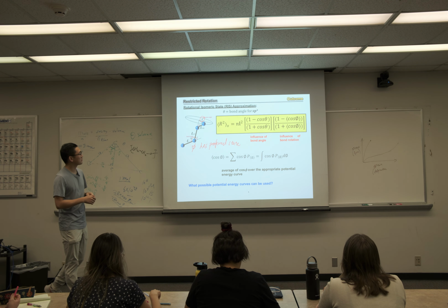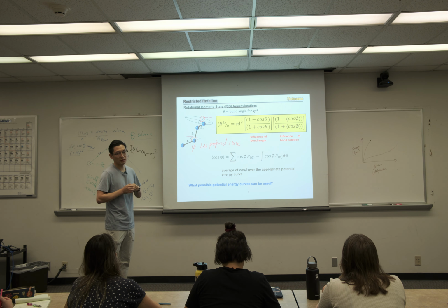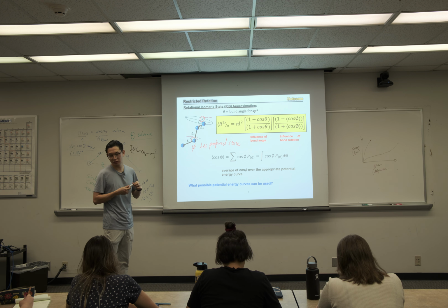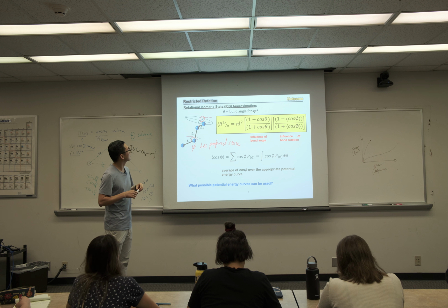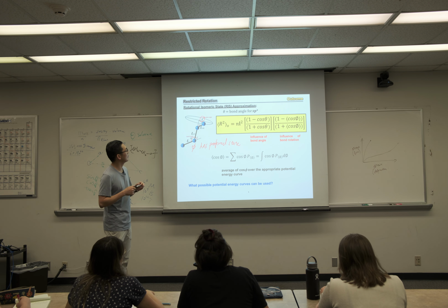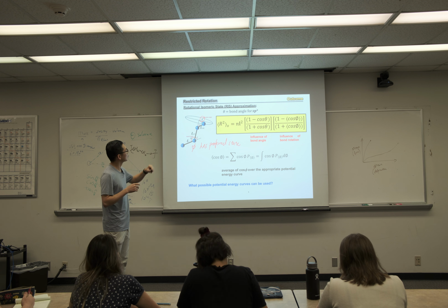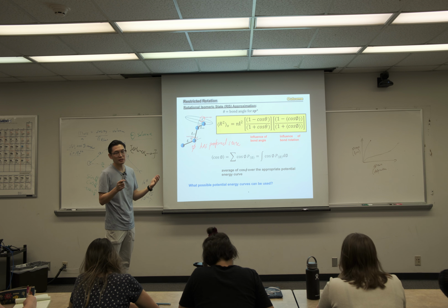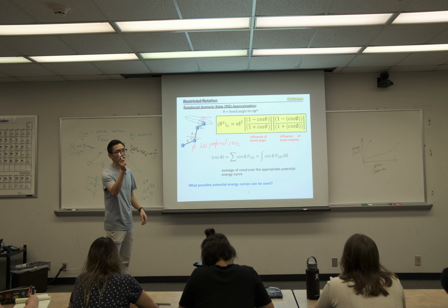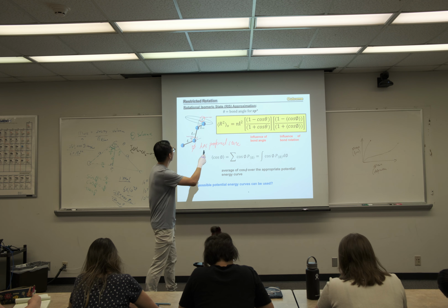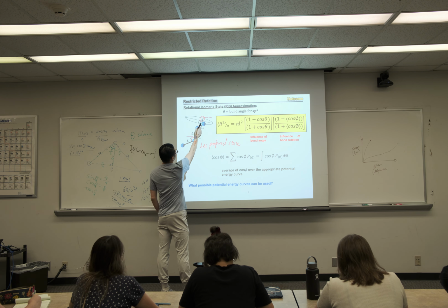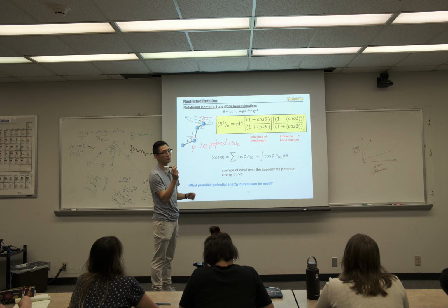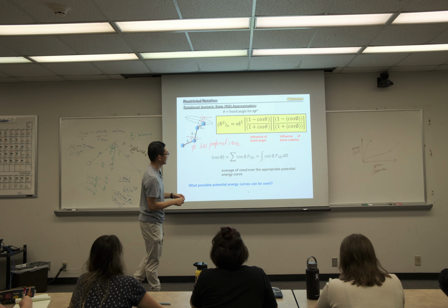So this is the restricted rotation we talked about briefly. Now when phi is restricted, in addition to theta, we enter into what some people call the rotational isomeric state, which is basically the same as the hindered rotation state. In this case your theta is fixed, but now the dihedral angle phi has a fixed number too, because of which direction they want to rotate to.